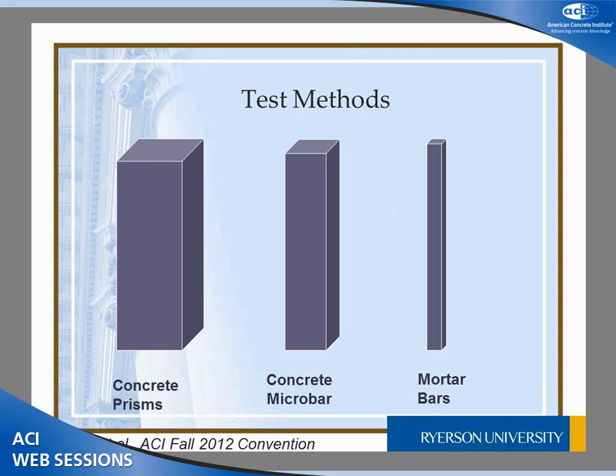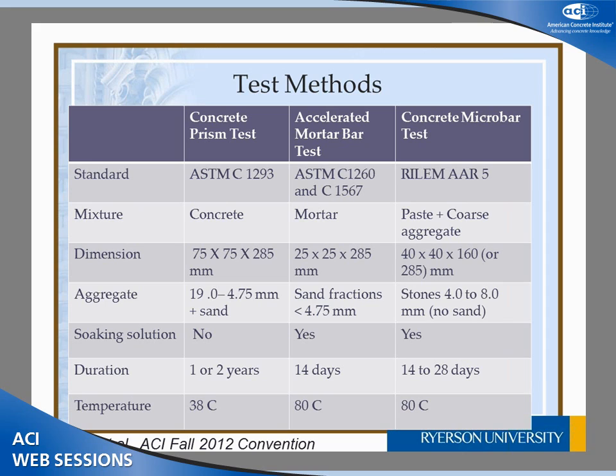The accelerated mortar bar test gives results in just 14 days, but it uses a very high temperature of 80°C and an external source of alkali. You have to crush the aggregate to sand size. An advantage of the concrete microbar — which is not yet an ASTM or Canadian standard but is used in Europe — is that you don't have to crush the coarse aggregate. It uses paste (cementing material, water, and stone), and this is especially useful for alkali-carbonate reactive material, since crushing such material to sand size can suppress the reaction entirely.